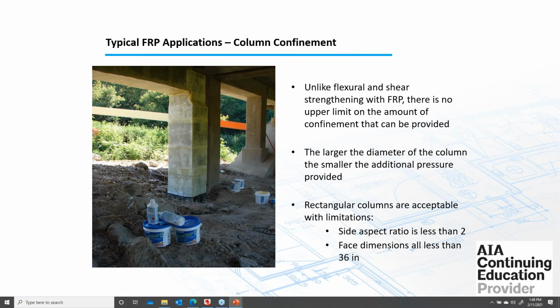You can do confinement for square columns. Obviously, we're showing one here. There are limits to that. I'm not sure what the CSA is, probably similar, but in the ACI, the side aspect ratio has to be less than 2, which means no one side can be more than 2 times larger than the other side. So if you had, say, a 36-inch by 12-inch column, you can't confine that with FRP. You'd be limited to a 24 by 12, or if it was 36, the other side would have to be 18 inches. Pretty simple math. And then no face can be larger than 36 inches. So if it's a 4 by 4 foot square column, that's actually too large to confine with FRP. You're limited to 3 feet.